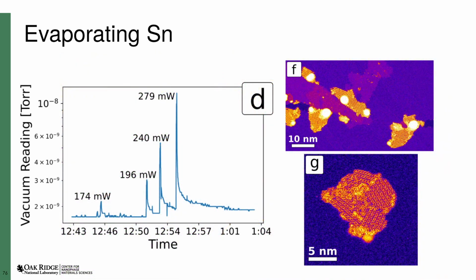the sample. On the left here, we have the vacuum reading through time as we increase the power output of the filament. The more power, the higher the vacuum spike, indicating we are evaporating more material. On the right are a couple of higher resolution images of the bright regions. It appears we have synthesized 2D tin nanoflakes. We are still working on figuring out the exact structure of these nanoflakes, but we have our first in-situ growth.